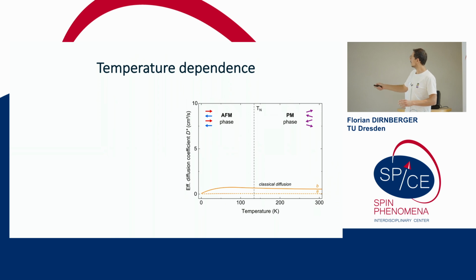We can again calculate this classical expectation where you can see this anisotropic diffusion, and we can make this quantitative. So these are the numbers that we expect for the effective diffusion coefficient. When we look at that in the experiment, the result looks quite different.